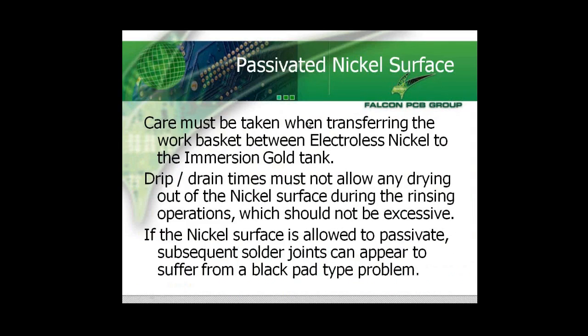And transferring the actual baskets between electroless nickel and the immersion gold tank can also be quite critical. Extreme care must be taken that drip and drain times don't allow any drying out of the nickel surface. What we tend to find is it appears to passivate very, very quickly, and although the gold will plate on top of it, you tend to find that you get a black pad type of appearance when trying to solder to it. The other thing we should do is rinses should also not be too excessive, or that can also cause problems.